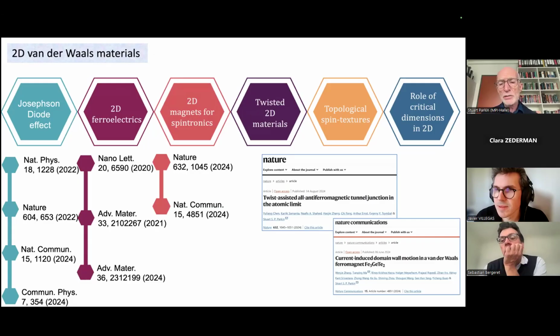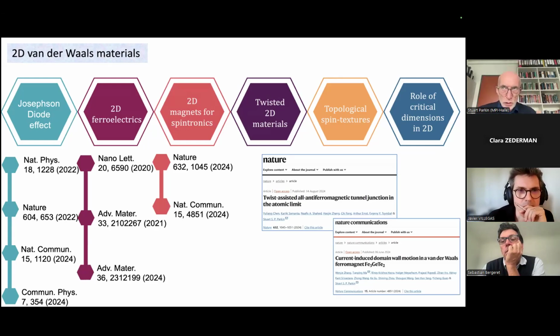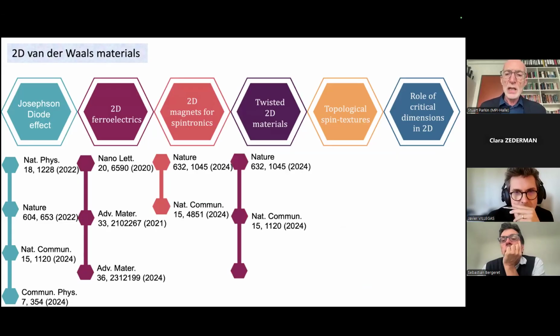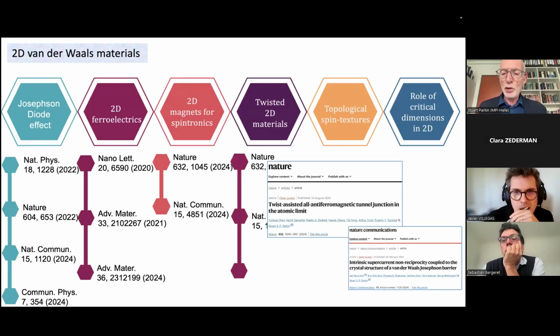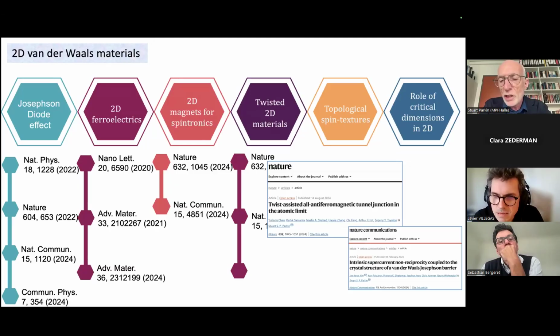And very recently, we demonstrated an all anti-ferromagnetic tunneling junction using a very special orthorhombic form of a 2D antiferromagnet, chromium sulfur bromine. This is the paper we published in Nature at the end of last year. And finally, in this same Nature paper, we showed that we could tunnel through twisted 2D layers, and this twisting destroys the innate anti-ferromagnetic coupling between these layers, allowing us to build very interesting tunnel junctions. And if there's time, I want to briefly discuss our work on twisted junctions for a van der Waals Josephson diode device.